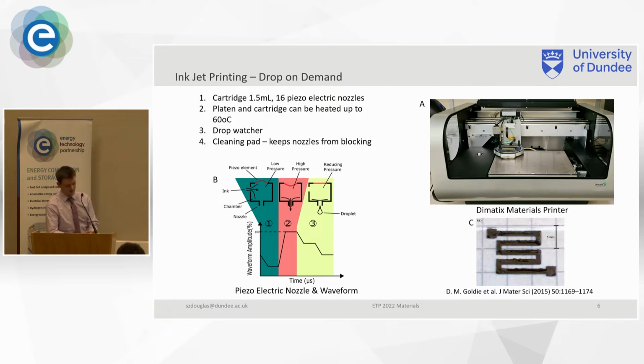And this is where we can do some cool stuff with the droplets in the nozzles. It's a camera that lets us see the nozzles on the cartridge, and on the cartridge is 16 piezoelectric nozzles. And through this camera we can see which ones are working. So some of them can get blocked, some of them can not jet correctly. So when we see the droplets, we want to make sure they're going in a straight line, not off at angles. And we also want to make sure the velocity is within an optimized zone of about, I think, 6 to 9 meters per second.